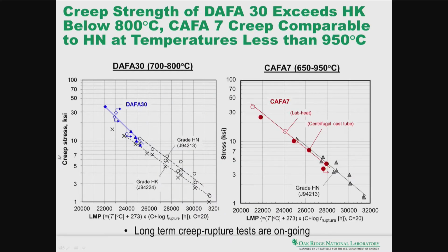So we are also accumulating creep data. We are still in the process of having more tests added to this as we speak. But what we show here is the Larson-Miller plot for DAFA 30, and also superposed on that is the HN and the HK data. And you can see that the DAFA 30 performs comparable or better than the HK at temperatures up to about 800C. Again, remember that at temperatures above 800, close to 900, the strength is going to drop off pretty rapidly.